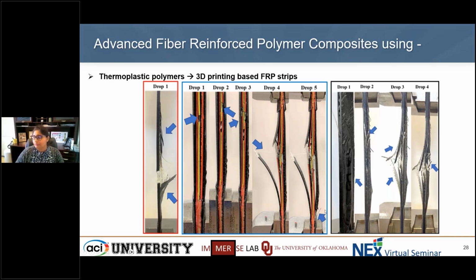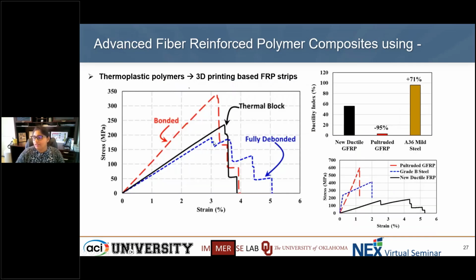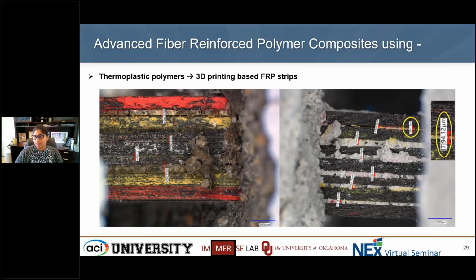rightmost layer. This is in terms of another bond where we see only certain drops. So the highest number of drops is achieved in this fully debonded configuration. So hopefully with 3D printing, we can achieve some kind of filamentous debonding where we are still able to do that shear transfer, but not in an abrupt fashion, so as to improve the delayed failure or progressive mechanism of FRP composites. We've taken these FRP composites and put them in concretes because our focus is primarily civil infrastructure.